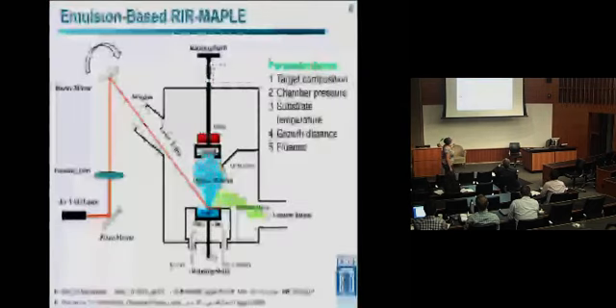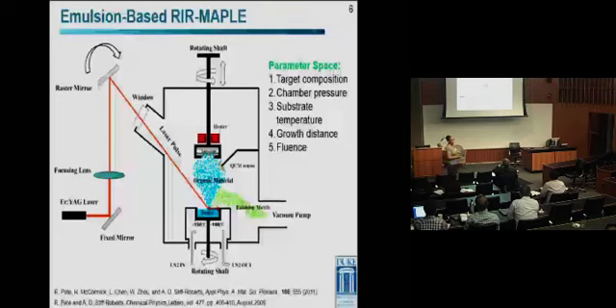So this technique, emulsion-based RIR-MAPLE, is a variation of pulsed laser deposition. So it's a vacuum deposition technique. There are two big differences from your traditional PLD, or pulse laser deposition. One is that it uses an infrared laser as opposed to a UV laser. And that's important because now the energy from that infrared laser won't damage the organic materials that you're depositing. Another big difference is the target. So instead of having typically some type of solid ceramic target, we do have a solid target, but it's a frozen emulsion.